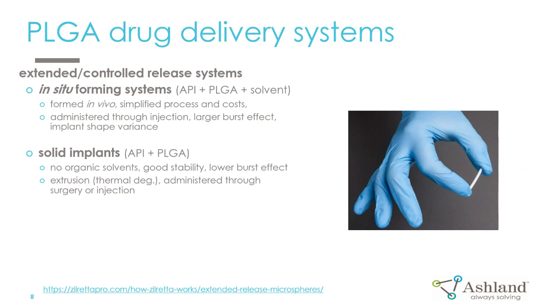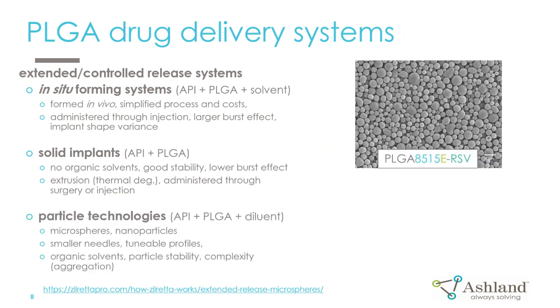In terms of challenges, these polymers are unstable, so that's a fact, and that's what you're taking advantage of. You're taking advantage of the programmed instability that you wish to use when you're formulating and delivering a compound. But with that in mind, if you're processing these at high temperature, you can degrade them considerably. So you have to be very conscious and mindful of that when you program and optimize your extrusion process. And I'll talk about that at the end of the slide set and show how that can be done.